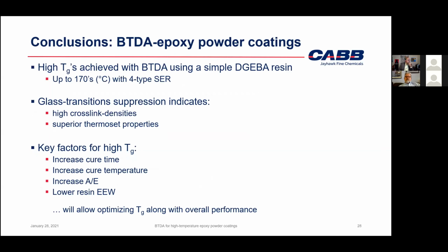So we just have a few conclusions. We were fortunately able to get some relatively contemporary resins from the industry, from our friends at Olin, and get high Tgs using the simple solid epoxy resins based on bisphenol A. And with this type 4 resin, we could get in the 170 Celsius range relatively easily. In addition to getting the high Tgs, we also noticed that when you cure these things in the right way, you can get Tg suppression as well, which tells you that it has a high cross-link density, but more importantly, that the properties of the coating would not change dramatically as the material is heated through the glass transition temperature itself.